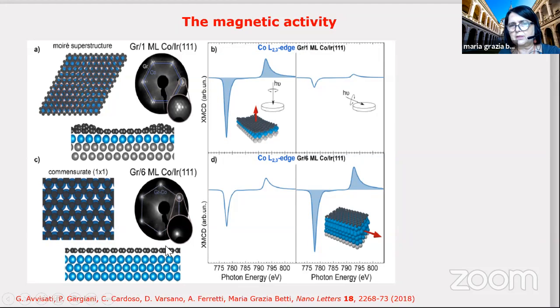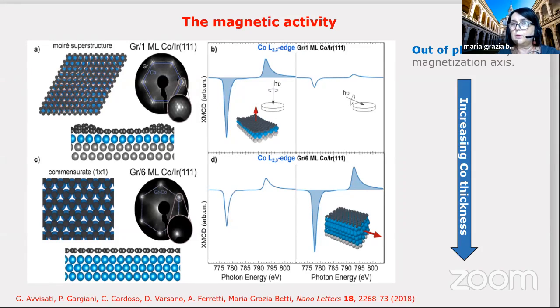The system is commensurate with graphene, and the dichroism changes because it's more intense in the other direction. So in this case, we will have the easy magnetization axis parallel to the surface. So with this, increasing the number of layers, we switch the easy magnetization axis.